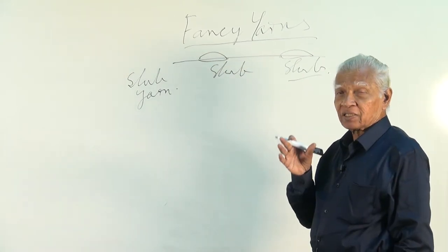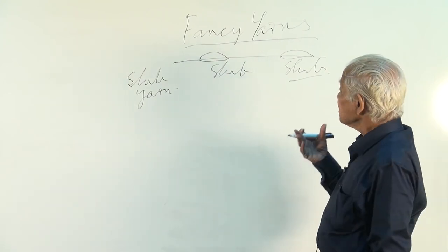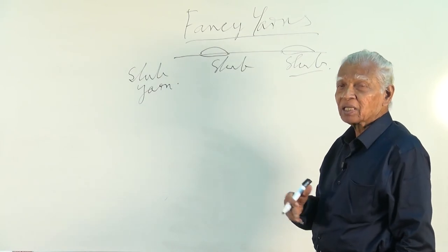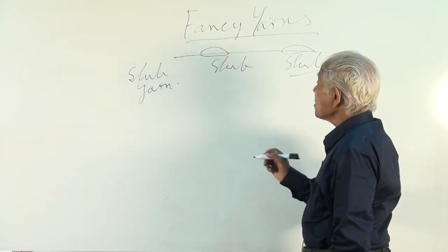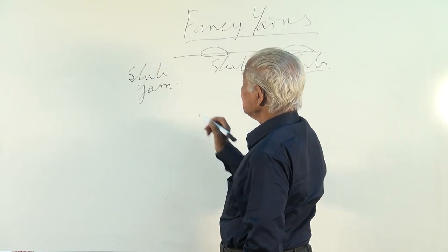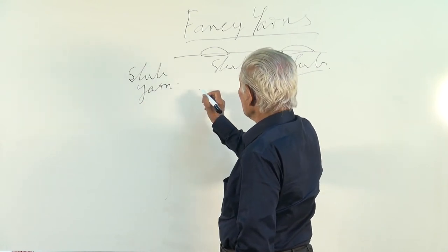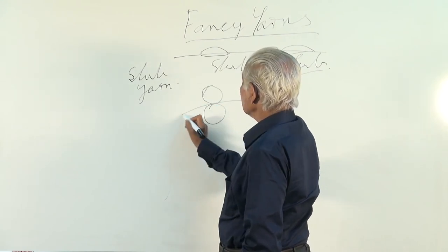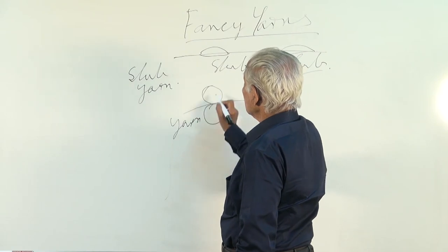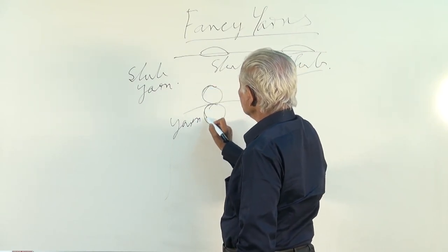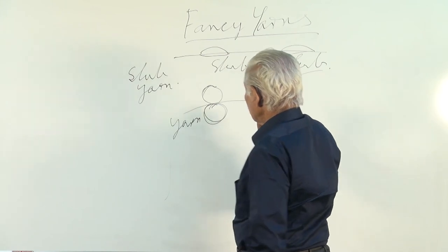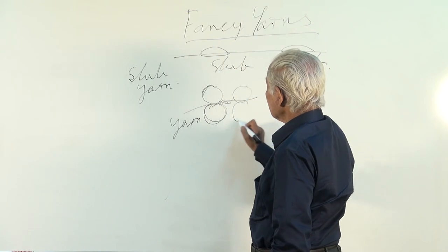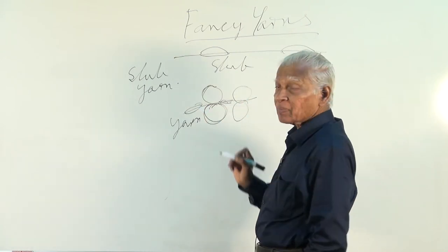Since weft yarns are subjected to lower tension as compared to warp, the blemishes that are present in the yarn, such as slubs, are present in the fabric as well. Now, there is a method to make slub yarn. There is a front roller of a ring frame which is delivering the yarn. Suppose the movement of the roller is prevented for a short time, then the material accumulates in the drafting zone and that is present as a slub.